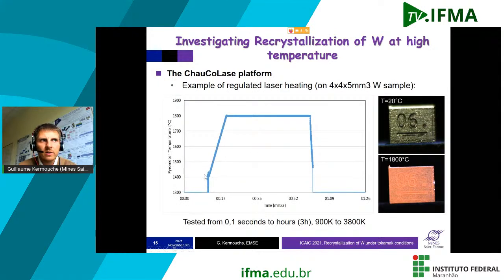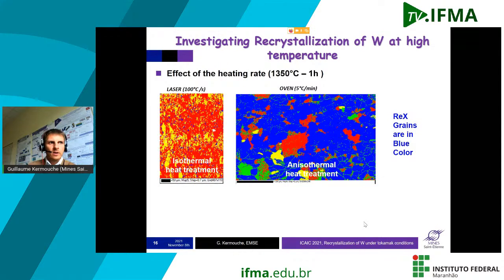Here you can see a test to show you that the regulation of the temperature is quite good. Here is the heating stage, and then you have the temperature regulation that can last 3 hours. So we can perform heat treatments from a few seconds to a few hours, between 900 K and 3800 K. So why use this kind of setup and not a classical oven that can reach very high temperature? It's because the heating stage has a significant effect on recrystallization of tungsten at very high temperature.